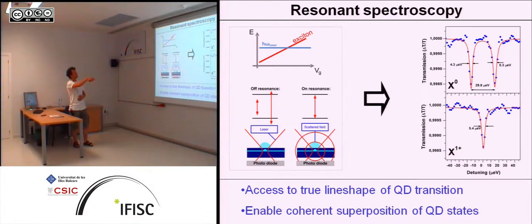So this now is basically the transmission spectrum of an X0 of the quantum dot at some gate bias, and then if you now go to a different voltage again, this is the X1+. So there's two holes and one electron in the excited state. So these are the two states we can easily access in a positively doped sample. Here you see the fine structure of the neutral exciton that is due to spatial asymmetry of quantum dots, but yeah, that's just a general feature which you can also use to distinguish between X1+ and X0. You see the linewidths here, they're all in microelectron volts, so 4.3 microelectron volt.